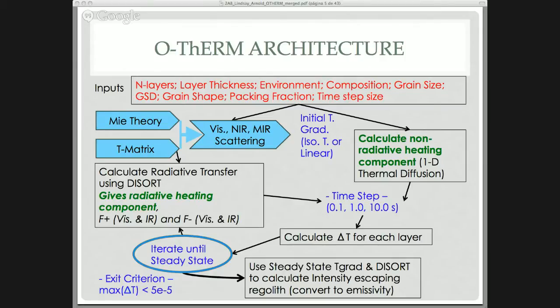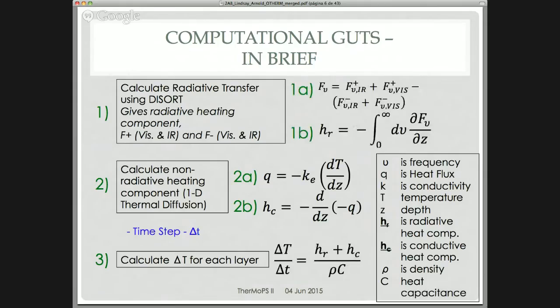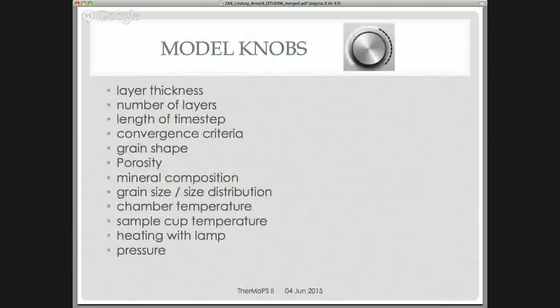And then we can integrate forward. We can do our time step, calculate a delta T for each one of the layers, feed that back in, and iterate until some sort of steady state temperature gradient is reached. This is defined by an exit criterion, which is variable. We use one where the maximum change in any layer is less than 5 times 10 to the -5 Kelvin. Then we can use that steady state solution, that temperature gradient, to calculate the outgoing intensity and convert that to emissivity. In the interest of time, I'm going to skip over some of the more computational guts because I want to show you some of the initial results of my exploring the effect of the temperature gradient.